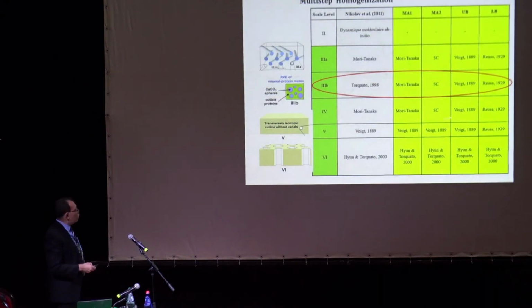So now with what Nikolov did, at these different levels he used the Mori-Tanaka at this level here. He used Mori-Tanaka, then Torquato, Mori-Tanaka again, Voigt and Torquato. This is just to account for porosity. Torquato here used a 2-point probability or statistical method, which is very complex. Actually, it's very difficult to determine those 2-point statistical properties. But what we decided to do is first just use Mori-Tanaka rather than this. And the second thing we decided to do is, instead of using Mori-Tanaka, let's use the self-consistent everywhere, except that here at this level, when we have to average all these plies, we just use the lower bound estimate.